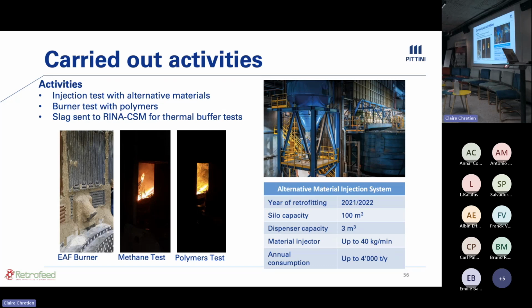These are the activities that we carry out in our retrofit project. And of course, we had several trials with the injection of several feedstocks and materials inside our furnace. And we also had trials with a burner using polymers in our furnace, as you can see in the image below. And of course, we sent the slag samples to RINA in order to have the thermal buffer test. And on the right part, you can see our injection system, which is a silo with a capacity of 100 cubic meters. We are able to inject around 40 kilograms per minute of material, with an average consumption of around 4,000 tons per year of materials.